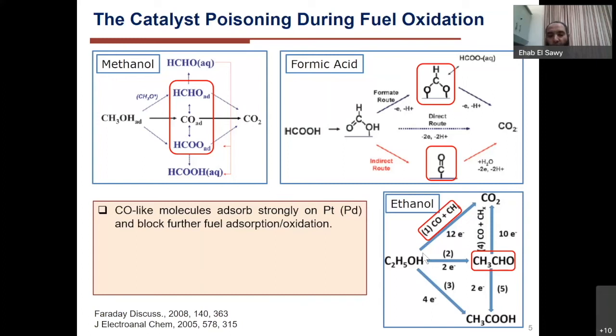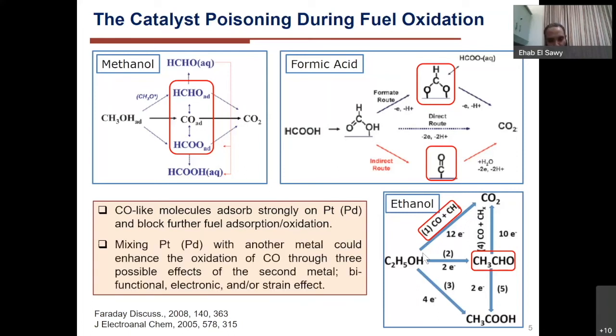So in order to solve this problem, modifying the catalyst with a second metal, alloying the platinum or palladium with the second metal, is one of the solutions. And that second metal usually affects the platinum catalytic activity through one or all of the following effects, which are the bifunctional effect, electronic effect, and strain effect. And I'll explain them in the next slide in detail.